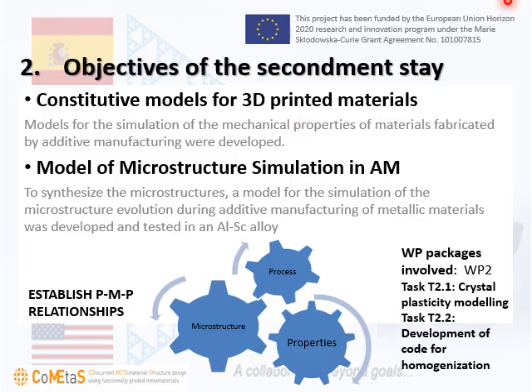In the part corresponding to the project that we're performing in the secondments in Atlanta, we have developed constitutive models for 3D printed materials. In particular, we have developed a crystal plasticity finite element model to predict the mechanical properties of these materials. These models require information regarding the structure of the material, or better said, what we call the microstructure. The microstructure itself is the aggregate of crystal defects, orientation, and phases of the material. This information is necessary because the microstructure itself provides the state variables for the constitutive equations.